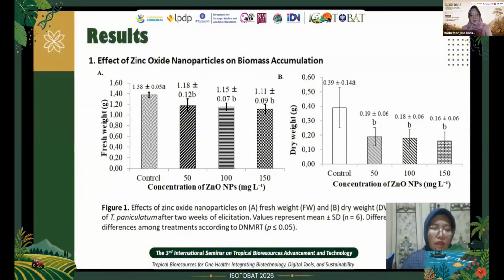Fresh weight and dry weight, like figure 1, were significantly affected by zinc oxide nanoparticles. The control group exhibited the highest fresh weight, whereas nanoparticle treatments resulted in significantly lower fresh weight values. Fresh biomass declined to 1.18, 1.15, and 1.11 at 50, 100, and 150 mg per liter, respectively, with no significant differences among nanoparticle concentrations, and figure B shows a similar trend here.